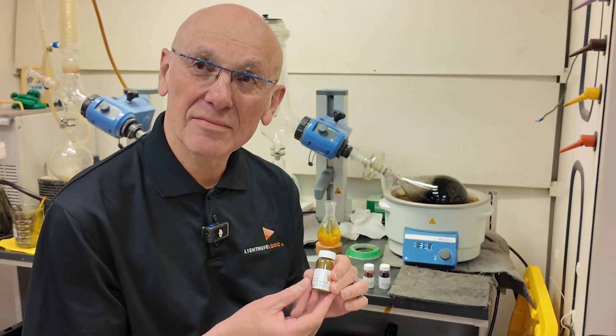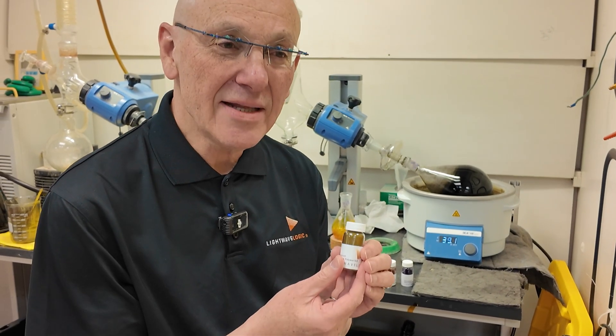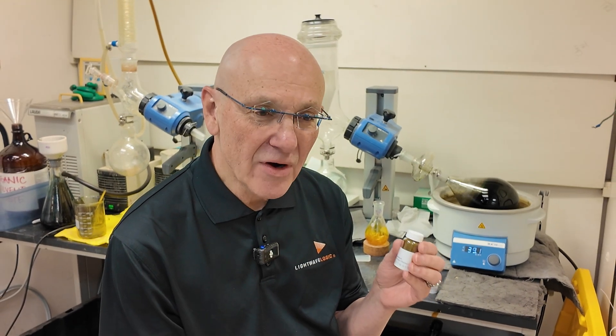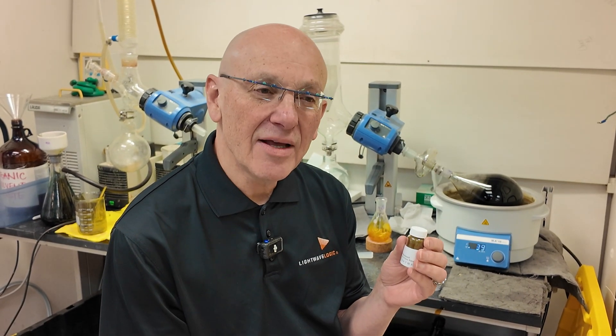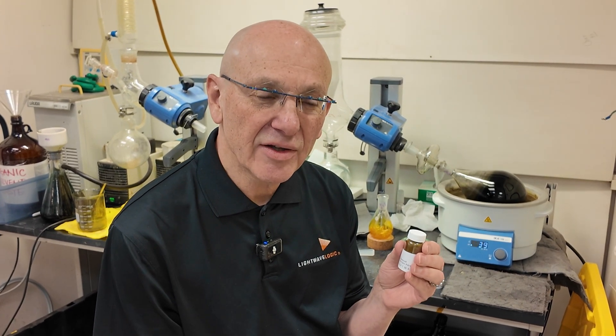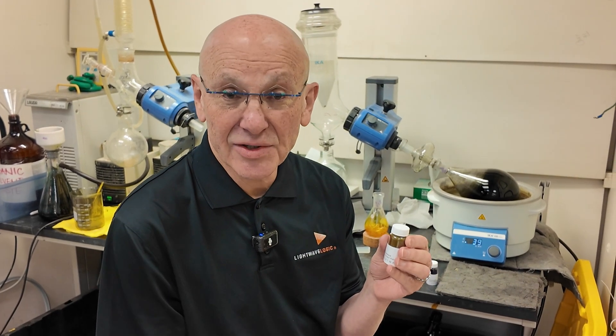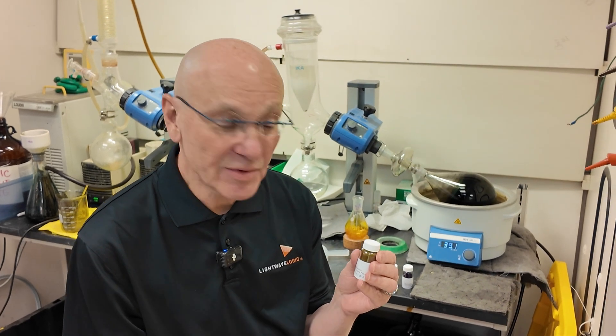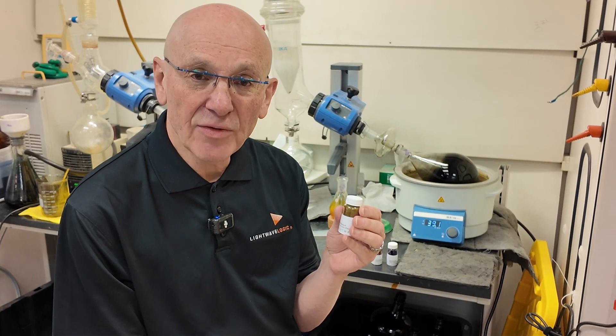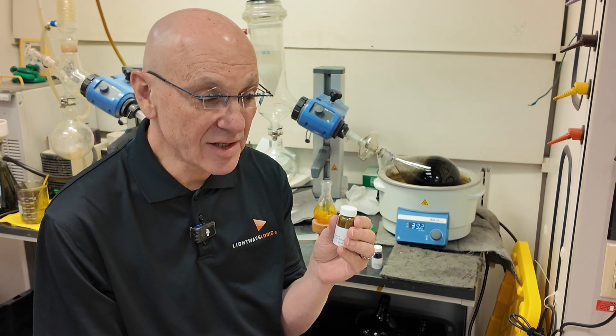This is the organic polymer everyone is talking about. Why now? Why do we need this now? We need this now because the polymers have a very large optical bandwidth and they work at very low voltage, which means low power consumption. If you look at the demand created by generative artificial intelligence, which is asking data centers to increase data rates and lower power consumption — you put these polymers into slot modulators, they perform at 200 gigabits per second on less than a volt, and also at 400 gigabits per second on less than a volt.